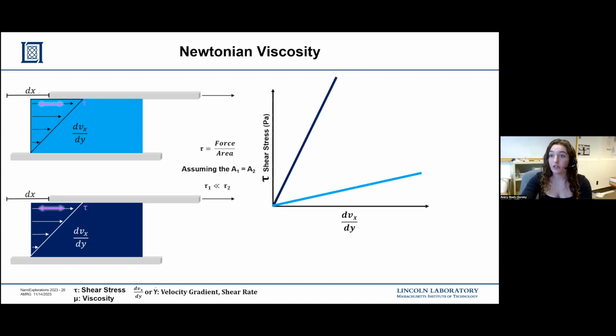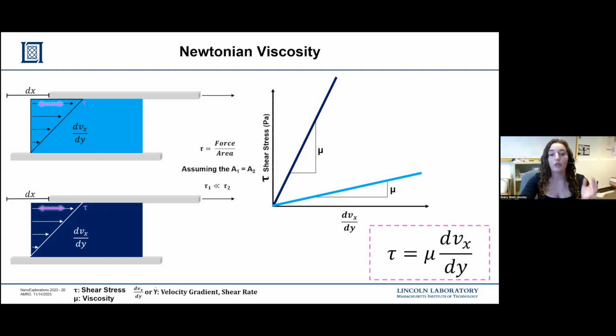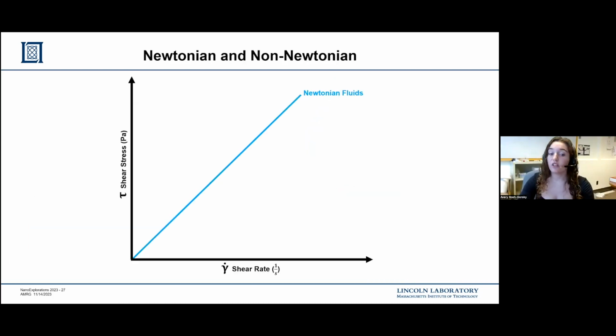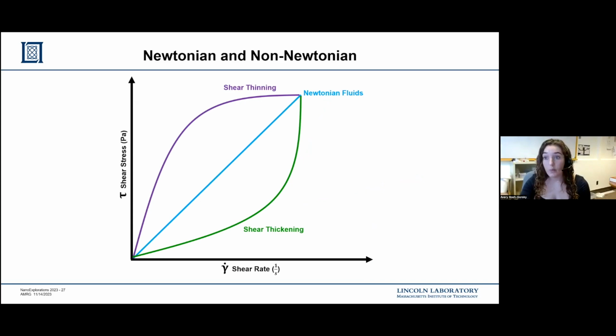So now we can plot our shear stress versus velocity gradient, and you get these two straight lines. The slope of these lines is the viscosity, and then you have the Newtonian viscosity equation, which is comparing your shear stress to the velocity gradient using viscosity as your proportionality constant. When we transition to fluids that don't follow these rules, we no longer use the velocity gradient as our x-axis. We're going to start using shear rate, which is defined by gamma. When we plot our shear stress versus shear rate for Newtonian fluids, we have this linear relationship. However, we have shear thinning and shear thickening, which are non-Newtonian and non-linear relationships.